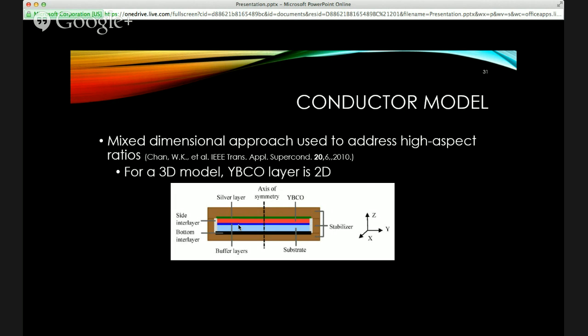And then if I'm going down, the green part would be a silver layer. Then the red would be the YBCO itself. Then the blue would be a buffer layer, which serves as a boundary for the YBCO. And the light blue grayish color is nickel. So the buffer layer is there to prevent chemical reactions between the YBCO and the nickel substrate. And then in this case, you have another buffer layer, and then you have another part of copper. So depending on the company, this can change. This just happens to be one that was used as a basis for my model, but different companies' formulas are different, depending on operation and trade secrets and things of that nature.